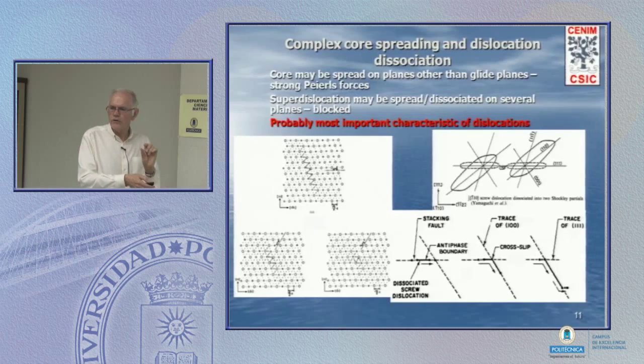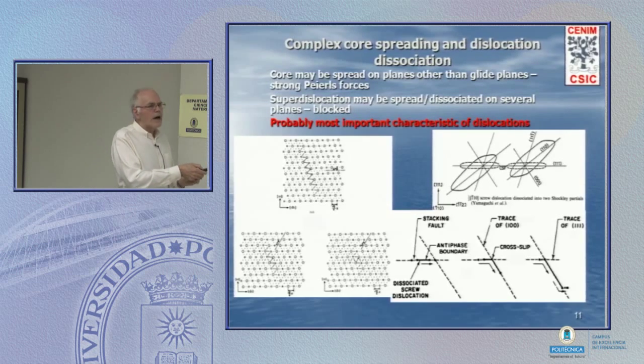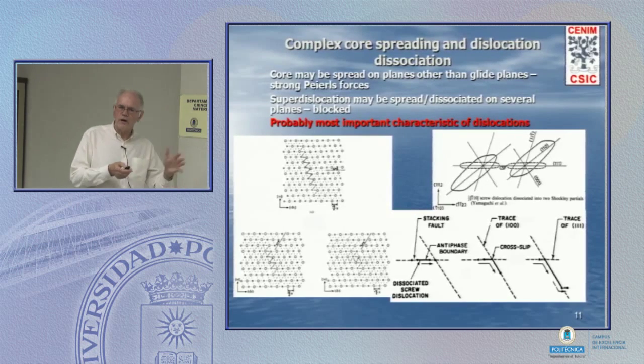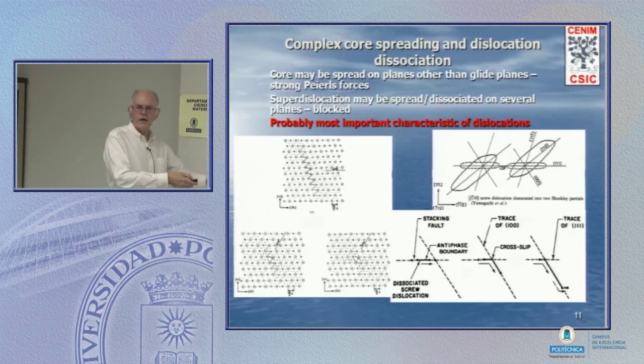The core relaxes over something like a nanometer, and because the elastic properties are anisotropic, directional, stronger in some directions than in others, the core spreads out in the elastically most floppy, the weakest direction. So the core looks like that, and here it looks like that. So the dislocation is now this three-dimensional object. There's no easy plane. I need thermal activation as well as a lot of stress to move it.